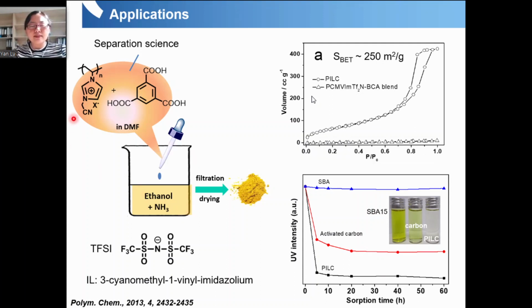One example is, again, based on this porous polyionic liquid. In this case, you mix this polyvinyl imidazole, using TFSI as a counter ion, with this molecule, because here you have this acid, and when you mix it, the acid will react with the ammonia and generate some pores in the final powder. And you can see here, for this polyionic liquid, you can get a specific surface area of around 250 square meters per gram. So this is also a kind of mesoporous particle.